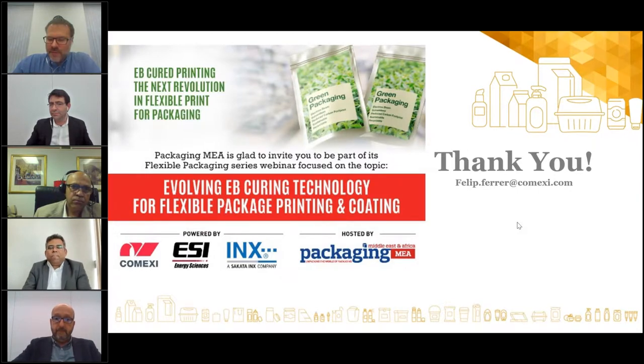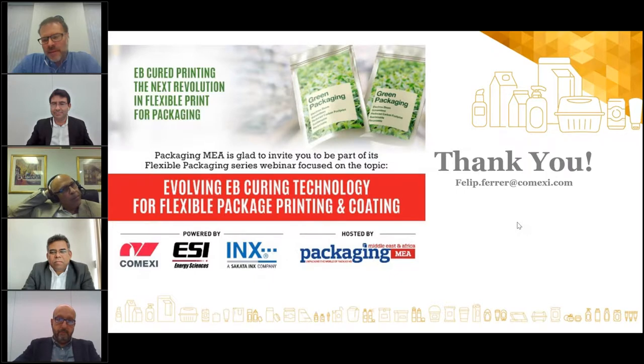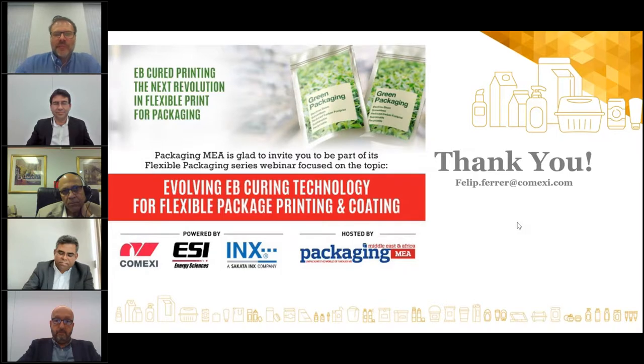Yeah, I can answer some of this. In terms of additions to the press, you'll need stronger pumps and maybe some different hoses. The viscosity of the flexo EB inks is a little higher than the conventional solvent inks, so you might need some stronger pumps, some stronger mixers, perhaps. And make sure that the hoses used are compatible with the EB inks. The other thing that might change would be the doctor blade assembly. You might need a stronger doctor blade, and there might be some changes to the doctor blade chamber that can improve performance. In terms of gravure EB inks, they're not commercially available at this time that I'm aware of.